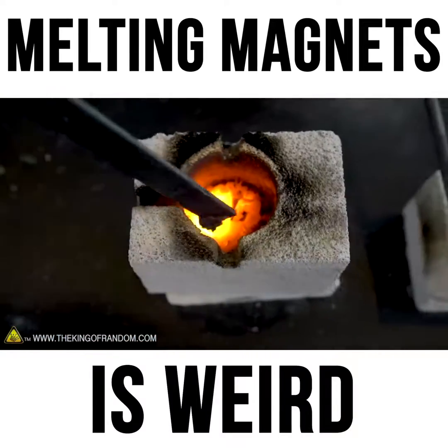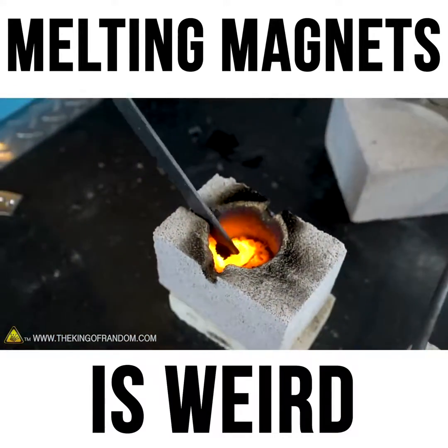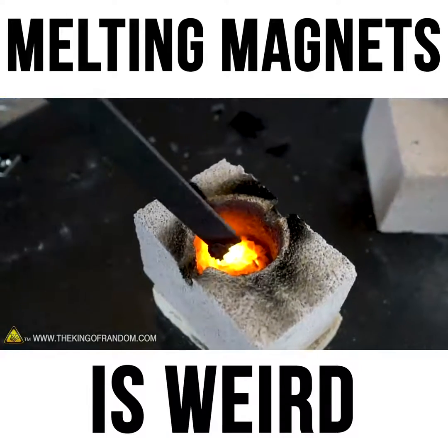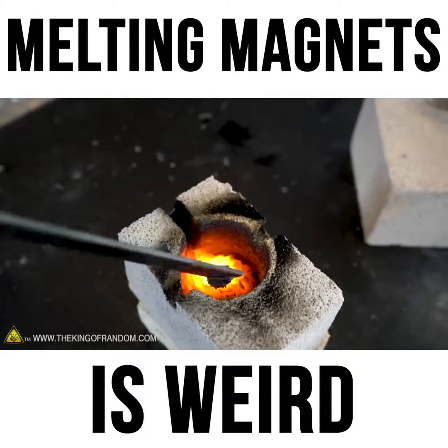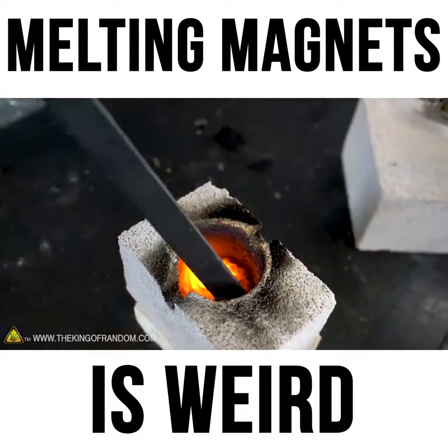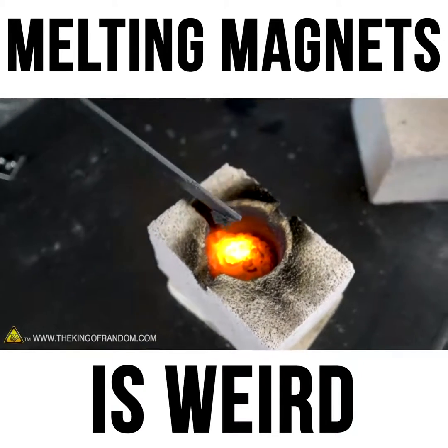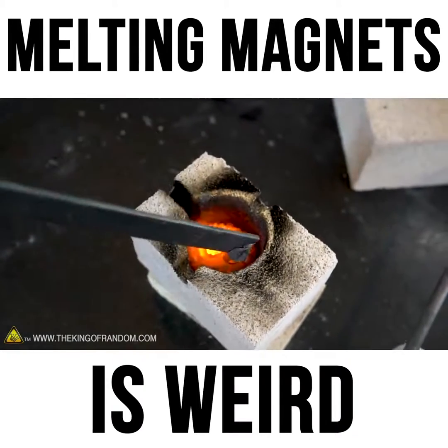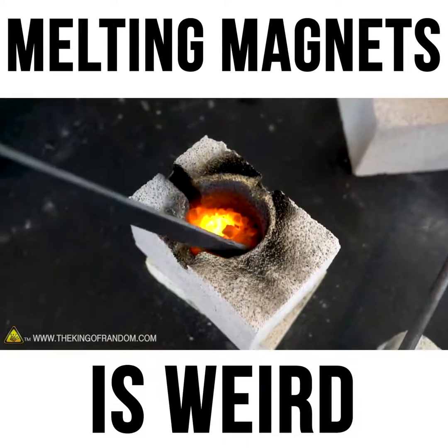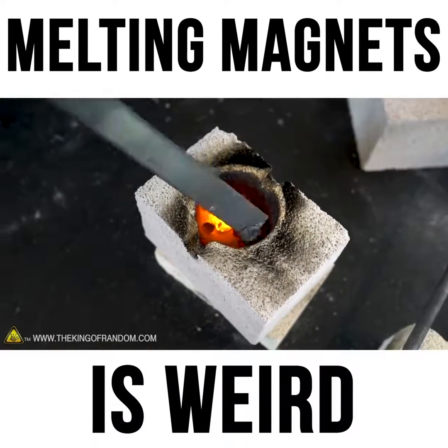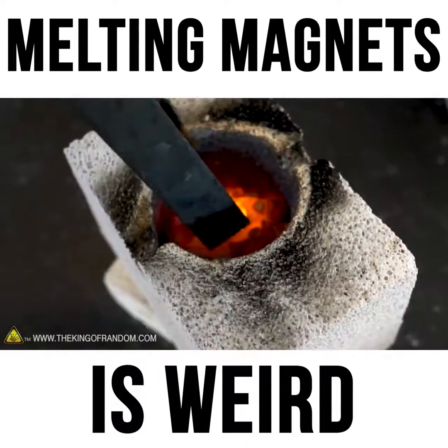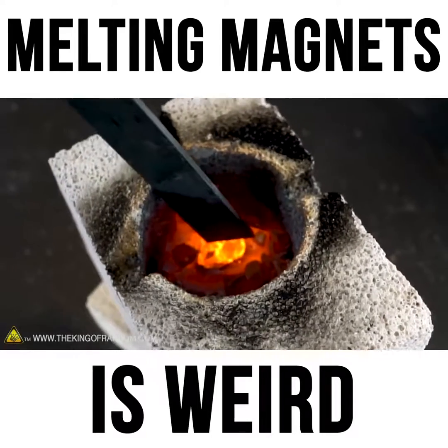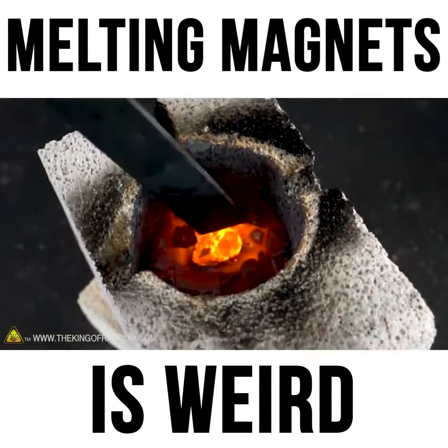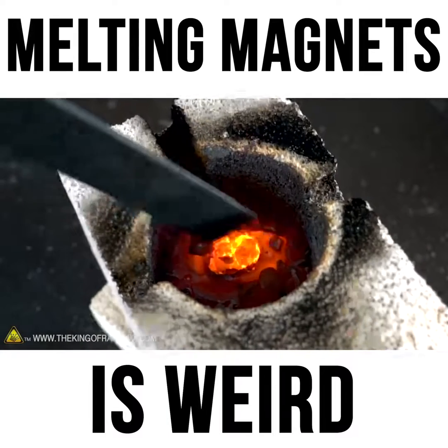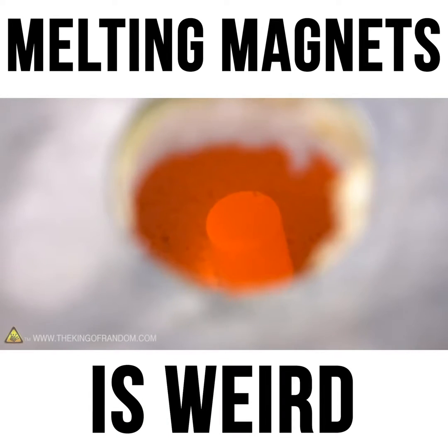There is some melted ferrite magnet, cooled down fairly quickly. It doesn't like to stay liquid, and it's kind of hard to direct the arc right at it because as it heats up, like it did in the other furnace, it just kind of shatters and goes everywhere. So it doesn't like to stay in one place to be heated up nicely, but it does melt. And like all the other magnets we've tested, as it melts, it really loses all of its magnetic power, no longer attracted to steel. Melting metal in magnets really does seem to ruin the magnetism that they have in them.